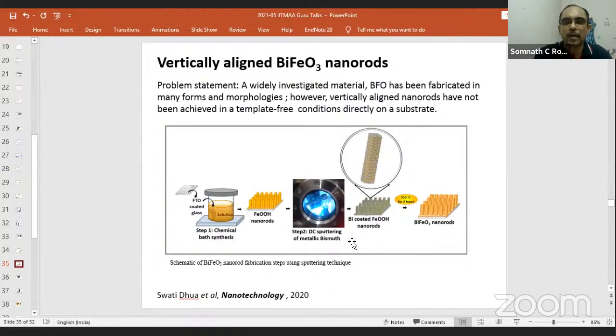What we did, our innovation, was that we put it in a coating chamber and coated it with a thin bismuth layer, very thin bismuth particle. So it becomes bismuth coated FeOOH. Then we did a very controlled thermal processing, and then we found bismuth ferrite nano. Again, one of the most beautiful works we did.